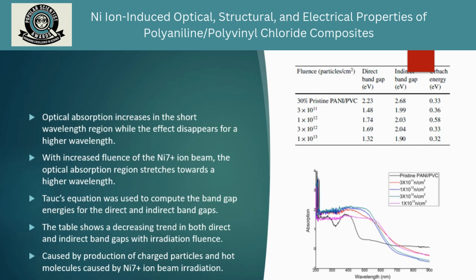The Urbach energy has been calculated from the slope of the linear part of the graph, the curves between energy and absorption. The table shows a decreasing trend in both direct and indirect bandgap energy with irradiation fluence. It may have been caused by the production of charged particles and hot molecules due to nickel 7+ ion beam irradiation. As the beam traces its path through the polymer, it leaves behind hot molecules and other reactive molecules.